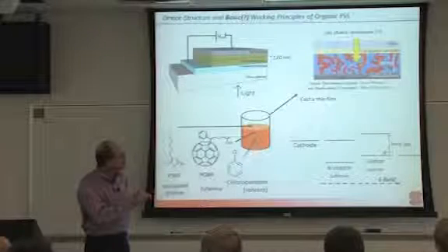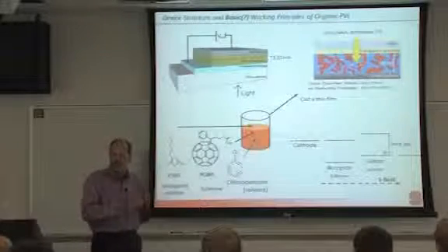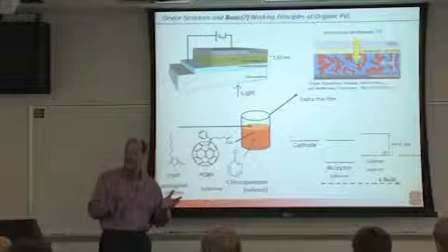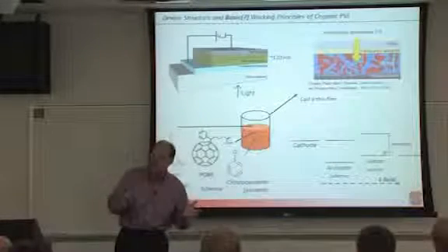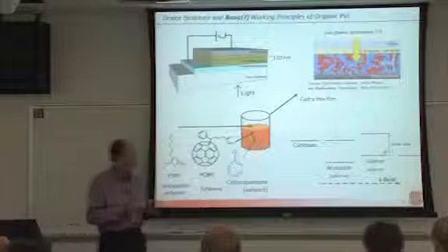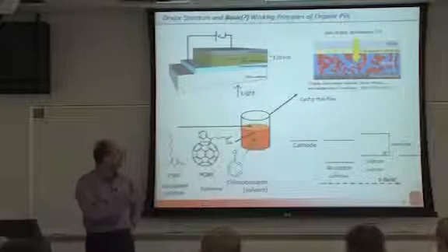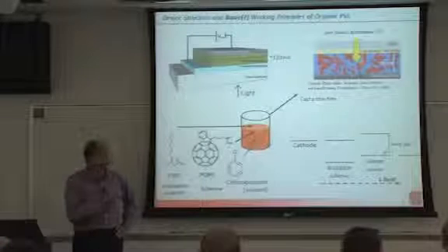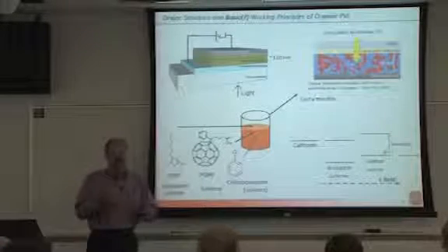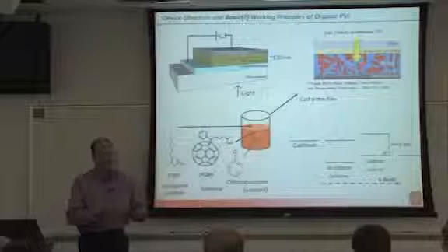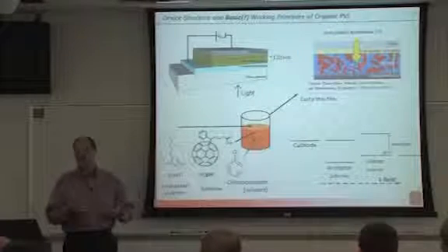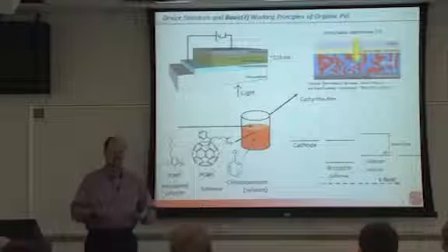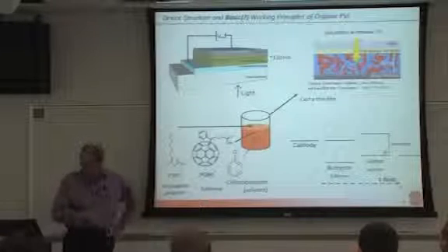And the engineering challenge is that the exciton diffusion length is only on the order of 10 nanometers, and the film thickness is on the order of 100 nanometers, and that means that I have potentially three-dimensional structures here. And so how do I measure that? And without measuring, how do I know what I get? Am I always stuck in a shake and bake mode where I sort of just heuristically change parameters?